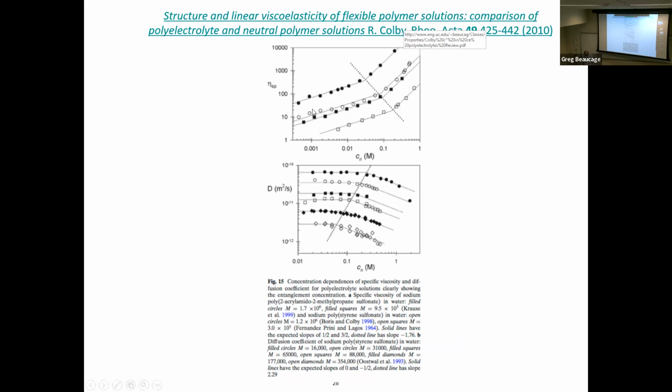You can do neutron scattering and measure the size of the coil. You can directly get the radius of gyration of the coil. And you know the mass of the coil, which you can also get from neutron scattering. The intercept at 0 for low Q gives you the mass of the coil too. So you get the mass and the size from neutron scattering. You can get the ratio of those two, and the cube of the size gives you the C star.